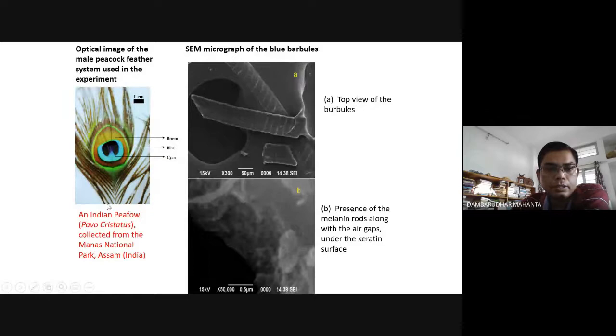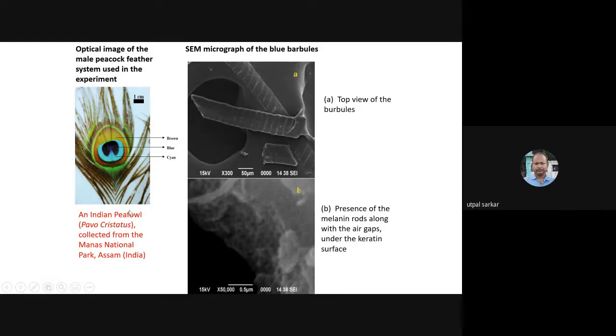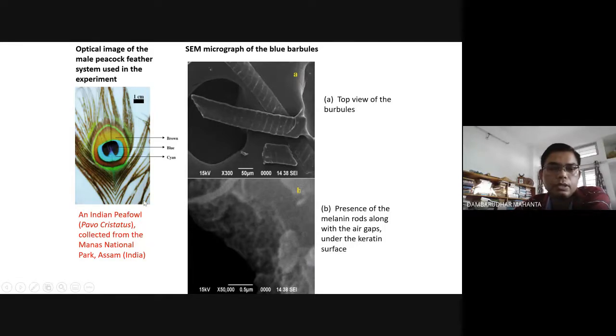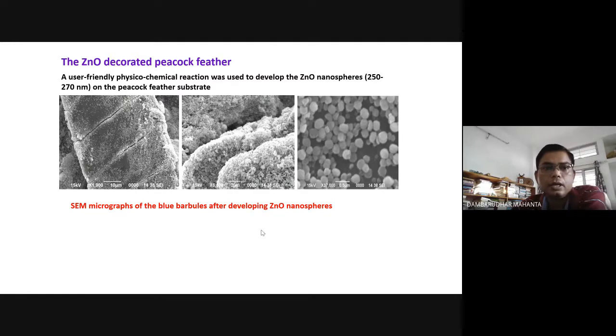This particular sample was collected from Manas National Park, like 10 years ago. We worked on this particular material. And here you see this cyan color, blue color, cyan color, and yellow color. You have three different colors. And the same image shows very good barbs and barbules. You could see that these are holes, porous structures, and these are now decorated with zinc oxide materials.